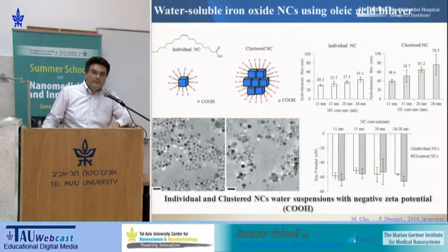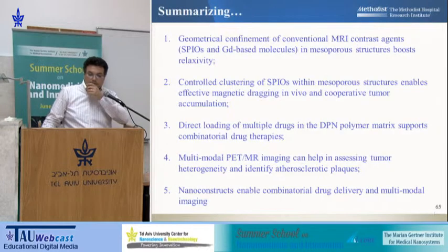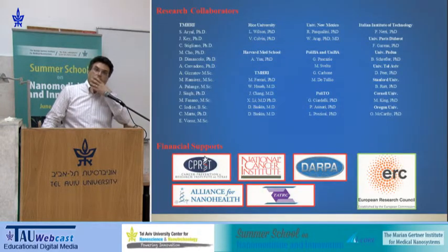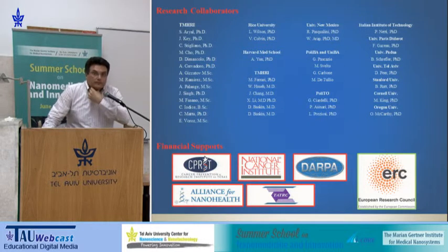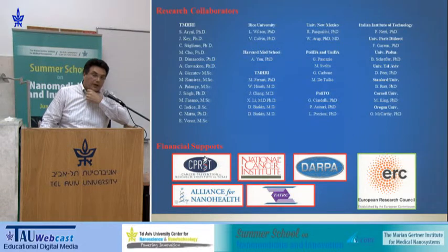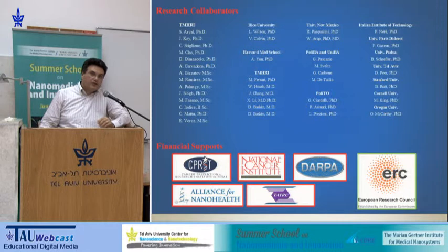One question. The main driving force here is the shear rate, and you made the point that the shear rate is definitely high. Elaborate on that. We expect that you have a lot of values in the shear rate. Yes, but the particles are big, in the micron size. So whenever you go above 100 seconds^-1, which is the minimal physiological shear rate, the hemodynamic forces on these particles will be too big for them to stably adhere to any other surface.